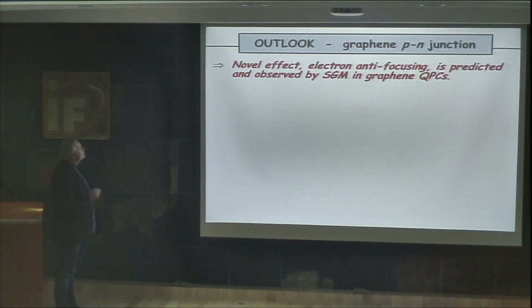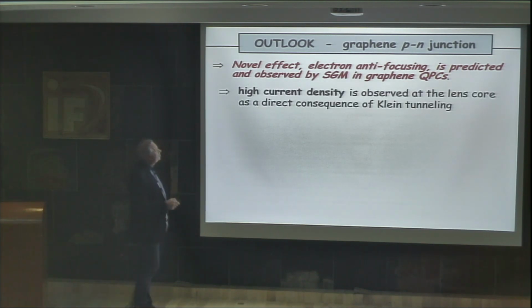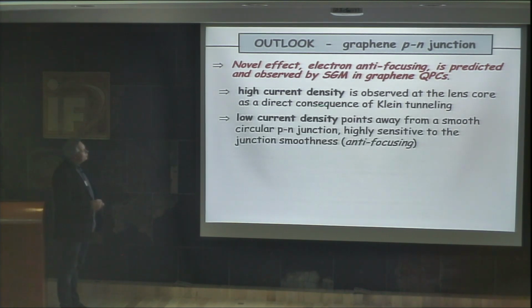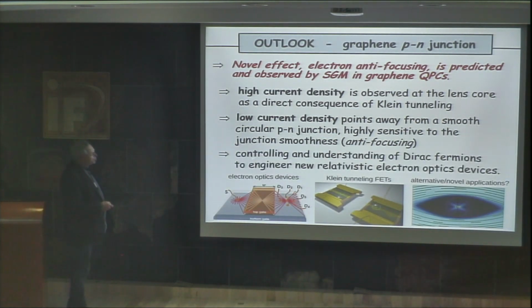So this is the outlook of the third part, sorry. It's a novel effect which leads to electron antifocusing, which is predicted and also observed by SGM in graphene quantum point contacts. So we have high current density observed at the lens core, as a direct consequence of Klein tunneling and the conservation of the pseudospin in graphene. We have low current density away from the point contact, from a smooth circular p-n junction, which is highly sensitive to the junction smoothness, as I showed you. Controlling and understanding the fermions is very important to engineer new relativistic electron optical devices, and we expect to find some application for this specific effect in the future.